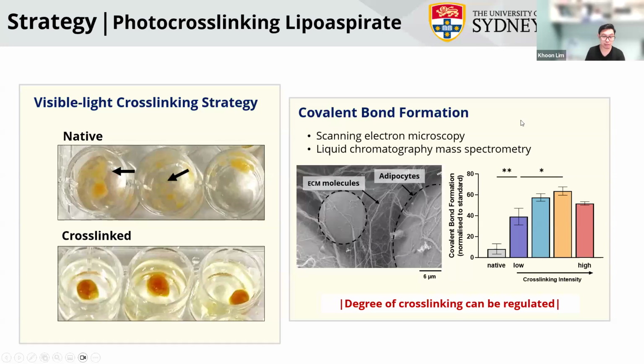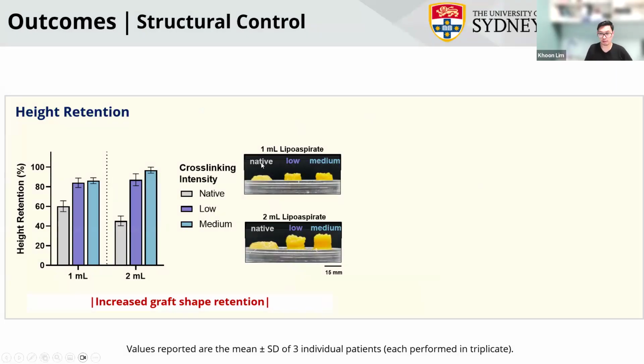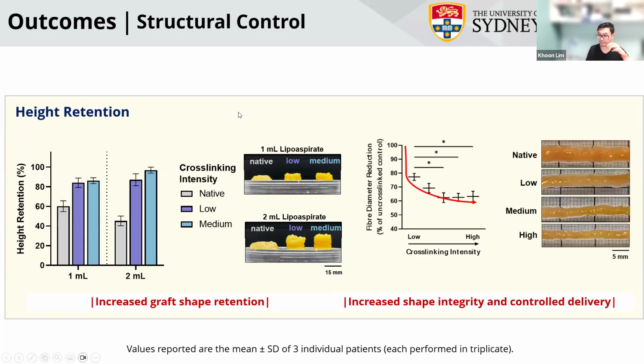So we thought that was quite cool, because if we form more of these covalent crosslinks, we have much better control over the shape of this native lipoaspirate. So this is just to show that you can now have fat that won't fall. So if you take native fat, 1 mil or 2 mil, you can never stack them up. They would just collapse. But if you now take native fat lipoaspirate mixed with our photo crosslinker and start shining light on them, you can see that even low and medium, you get better control over the shape. So you have an increase in the graft shape retention.